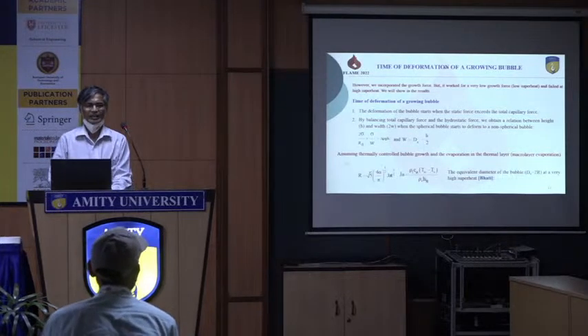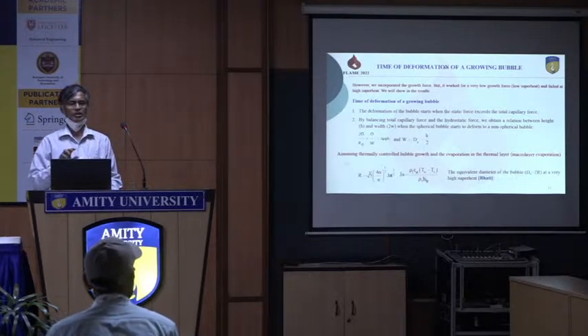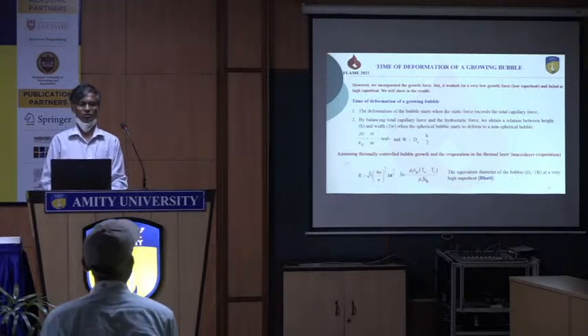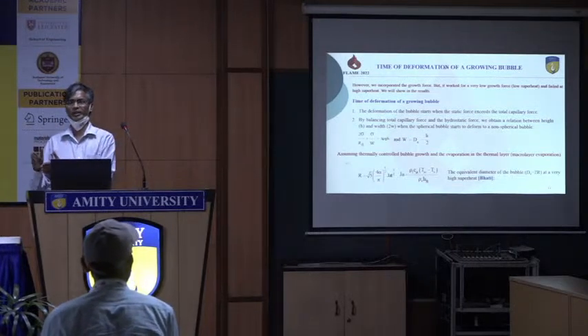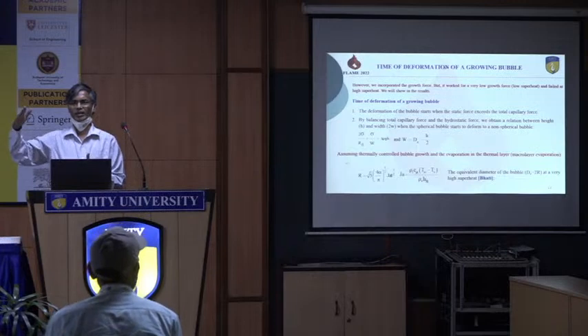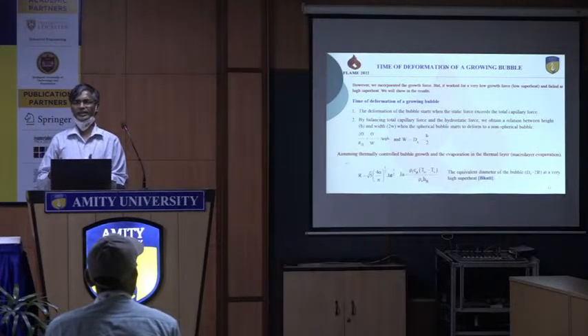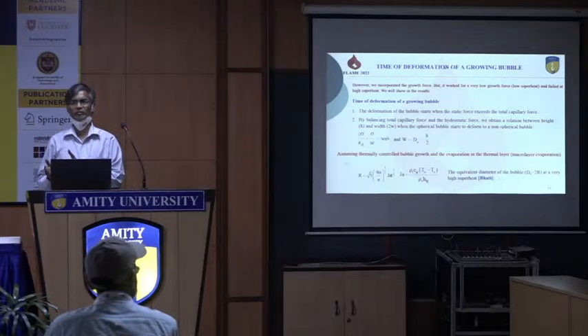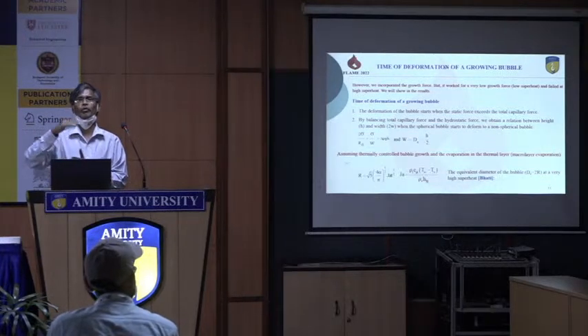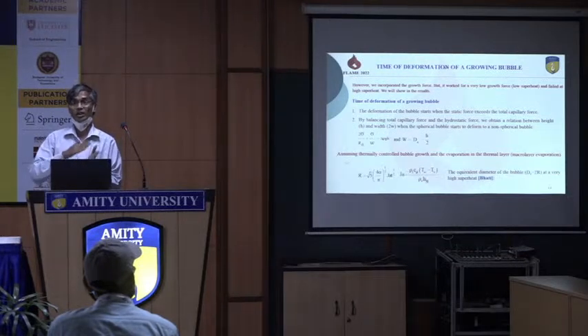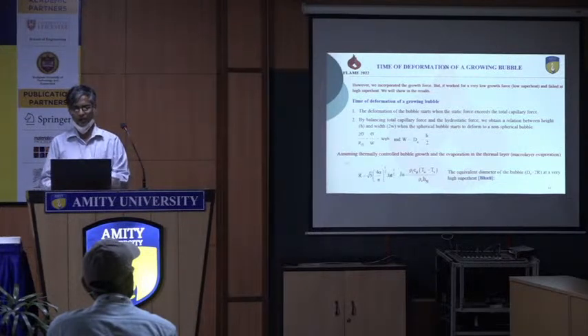All right. Now, what we have done for the time of deformation: we have found when it is deforming, in the growing stage, by applying the criterion that when the static force is greater than the surface tension force, then the bubble will start deforming. At that time, we can say the bubble is going from spherical to non-spherical. That is the indication, the criterion we have found analytically.